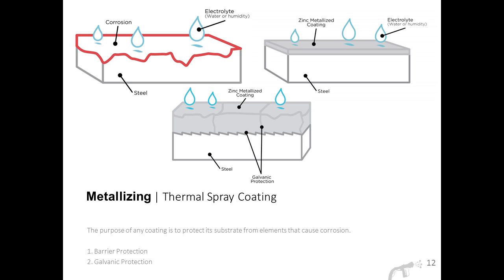But second, and probably the most important, is the fact that metallizing, certainly with zinc, provides galvanic protection. Metallizing is effective because the spray-on zinc sacrifices itself to protect the steel. The sacrificial protection is like the protection provided by zinc-rich primers or galvanizing. And essentially, this is really the reason why we use it, because if there's any occurrence of damage or any place where steel is exposed, the zinc will sacrifice itself in order to protect the substrate.